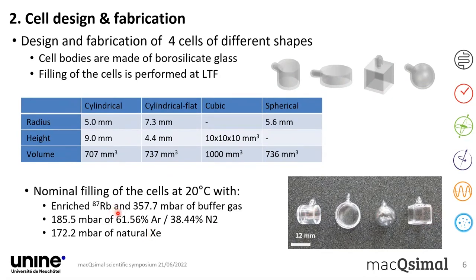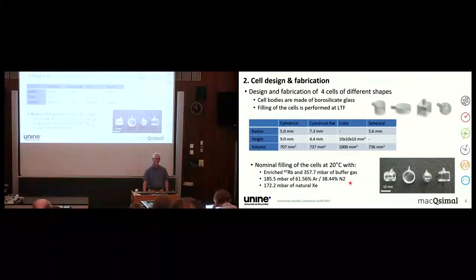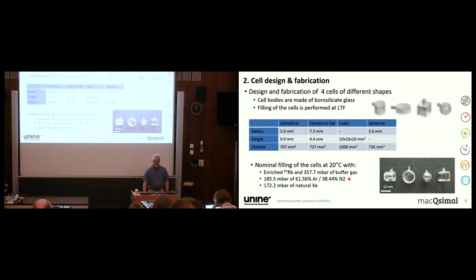What is inside is 87 rubidium and some 360 millibars of buffer gases, and there we used roughly 190 millibars of an argon-nitrogen mixture. The reason for using this mixture is, once more, we want to do clock measurements in order to characterize the contents, and the temperature sensitivity of the clock transition due to this mixture of buffer gas is strongly reduced around the operation temperature. And we add 170 millibar of natural xenon, and this will be then, in the gyroscope applications, the sensor for the rotation sensing.